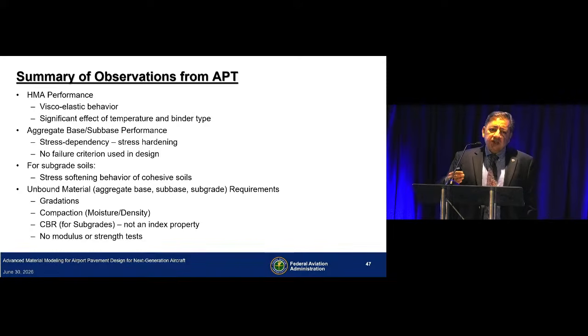Now, when you look at how are these materials accepted during construction, for aggregate materials, it's strictly gradation and the density is what is used for acceptance. No strength property is measured. And what are we using as an input property for a design? A modulus value. But that's something that we are not measuring. For subgrades, we are measuring CBR, which is not really an index property of the soil. And there are techniques available to measure modulus directly on top of the subgrade and aggregates, which could be used in a design procedure.